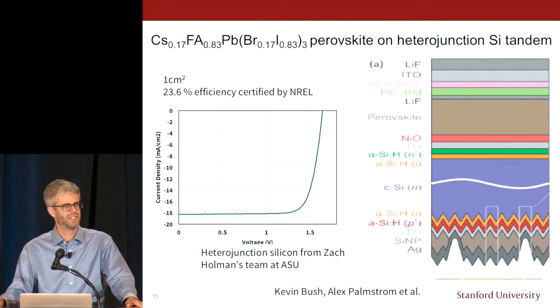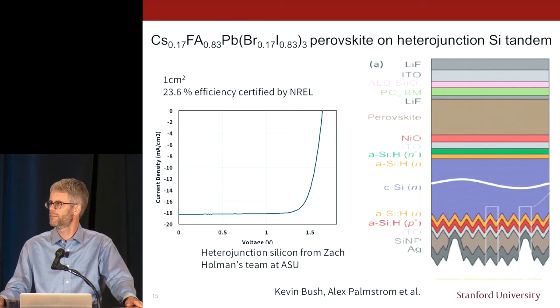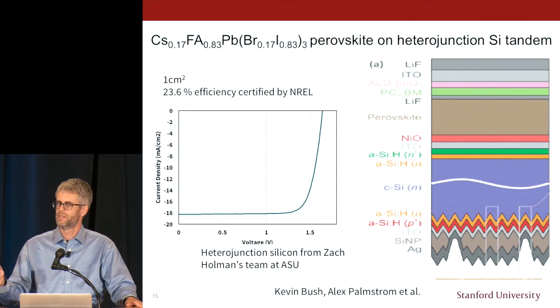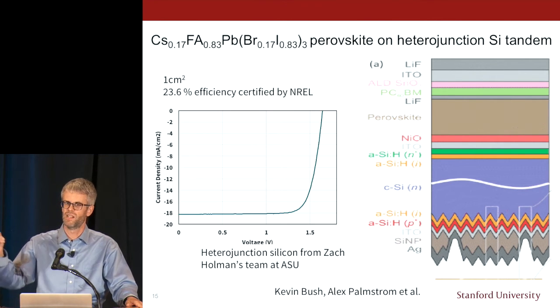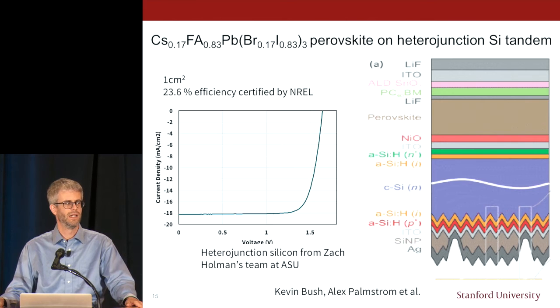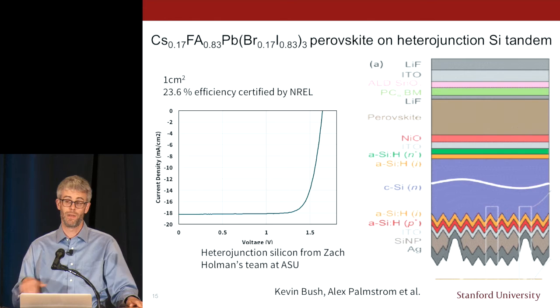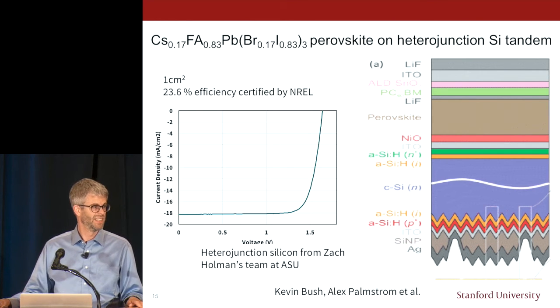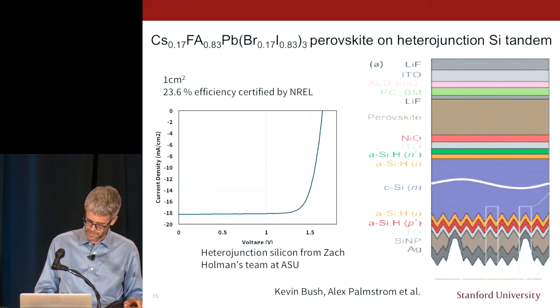I should also point out, this is a key number. That's a 21% efficient silicon cell on the bottom. So we've upgraded a 21% cell up to 23.6 using a perovskite that was only 15.5. And now we have better perovskites that'll allow us to get 26 or 27.